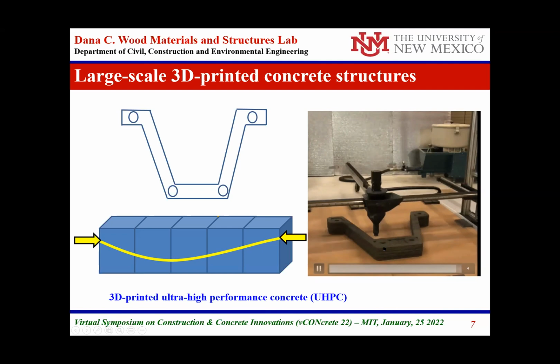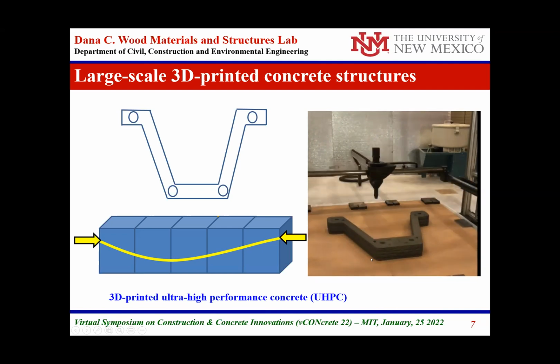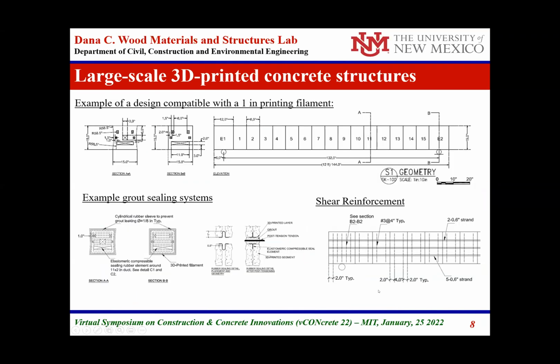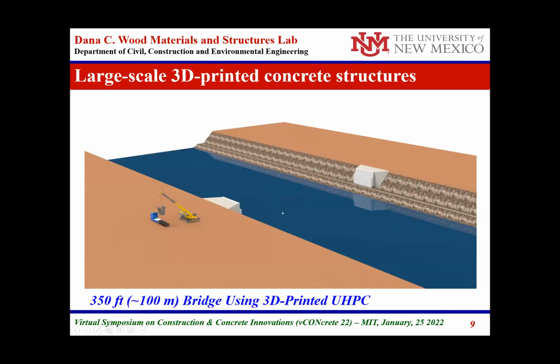Also interesting in printing is that you can change the profile of the post-tensioning location within the same section or across different sections. So this is an example of a bridge where we're laying out the way to do this post-tensioning, or this 3D printed concrete bridge quickly, with different segments, and some special segment joints designed to prevent water ingress into the bridge, and some of the post-tensioning going inside the bridge.